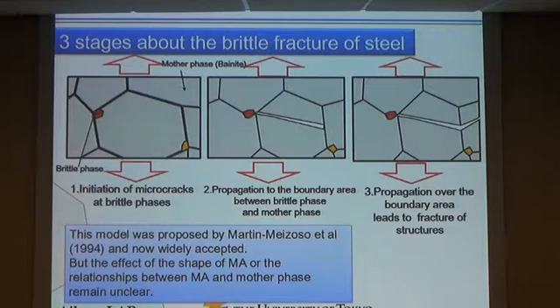Now I'll explain the three-stage model about the brittle fracture of steel proposed by Martin-Meizoso in 1994. The first stage is the initiation of microcracks at brittle phases like MA or cementite, and the second stage is the propagation to the boundary area between brittle phase and bainitic ferrite. And the last, third stage is the propagation over the boundary area, and this propagation leads to the fracture of structures. This model is now widely used, but the effect of the shape of MA or the relationships between MA and bainitic ferrite remain unclear.